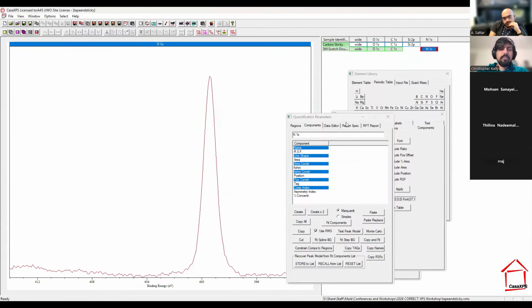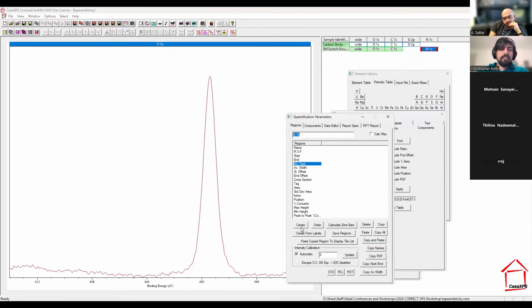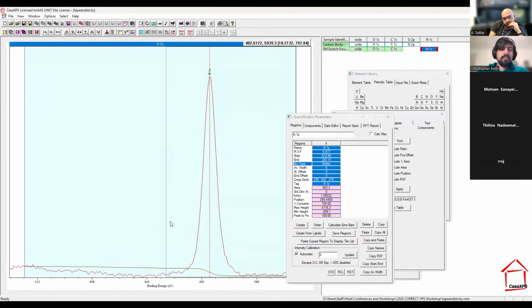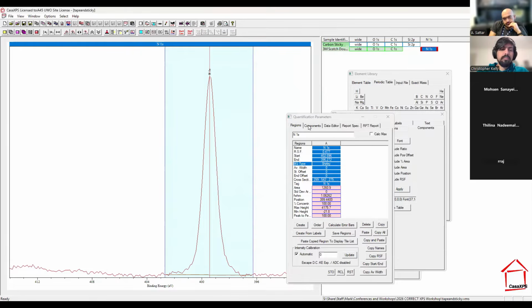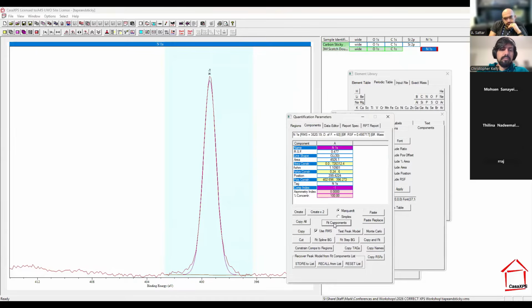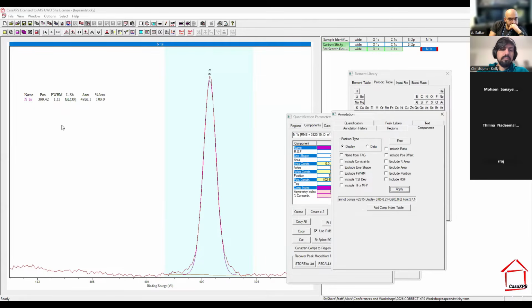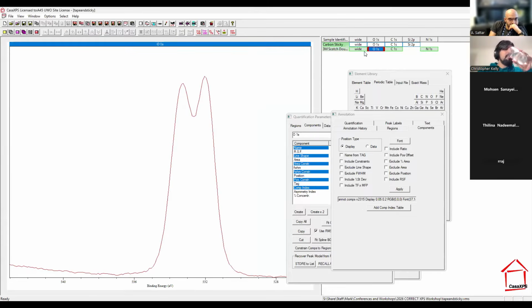So what's going on with our nitrogen? Again, we can apply a background, run that across our peak, fit in a component, see what its binding energy is, 399.4. So that tells us it's probably an amine or an amide type functionality within this material. So we've got that figured out. We go to the oxygen peak.